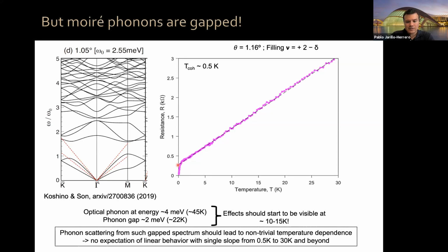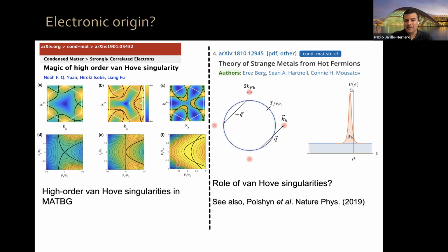So, a possibility is that electron correlations are responsible for this. So there's some electronic origin for this. There is a recent theory paper by Erez Berg and collaborators on strange metals due to hot fermions. And this is something where Van Hove singularities play a prominent role. And there are a number of papers that have shown that in magic angle graphene, you have a special type of Van Hove singularities called higher order Van Hove singularities, extra strong Van Hove singularities. Okay, so perhaps this is related.